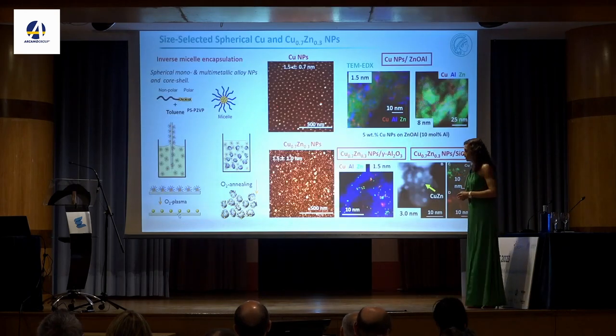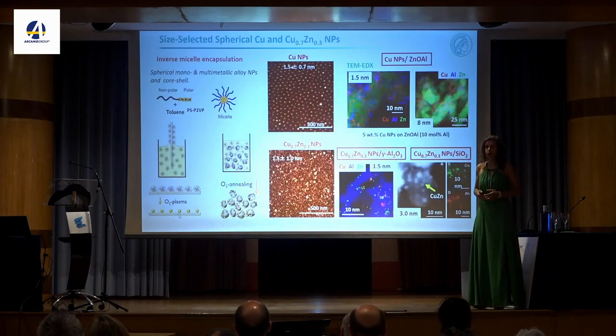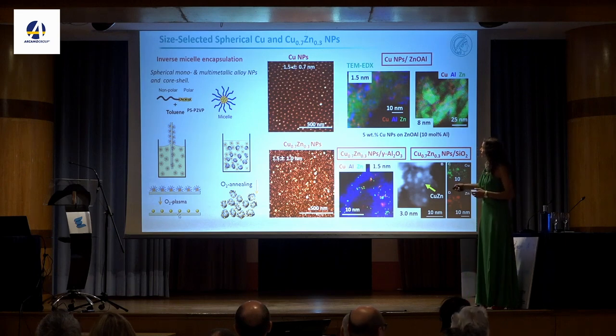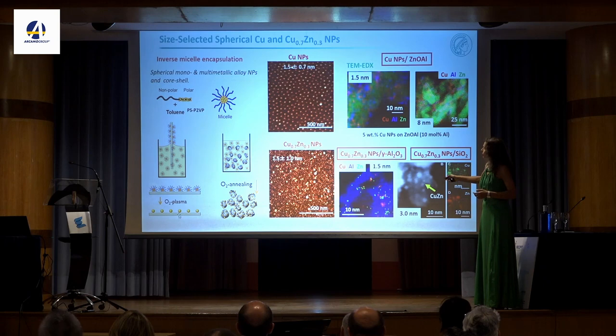So we start with a catalyst. So we use colloidal chemistry to synthesize well-defined size and shape control pre-catalysts. We can use block copolymers to make reverse micelles.